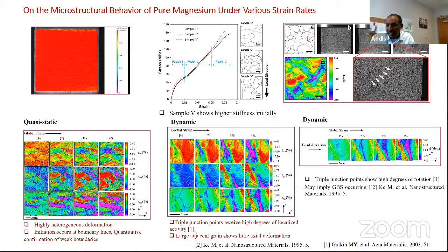But we clearly show that in the quasi-static conditions, the failure, especially the crack, happens in the grain boundaries. We showed that here. It's very clear here. As you see, this is the quasi-static and this is the dynamic response. In the quasi-static case, the response is heterogeneous. Again, initiation occurs in the boundaries. And this is a qualitative and quantitative confirmation of these weak boundaries in the quasi-static conditions.